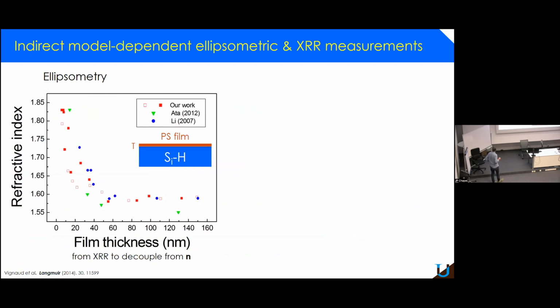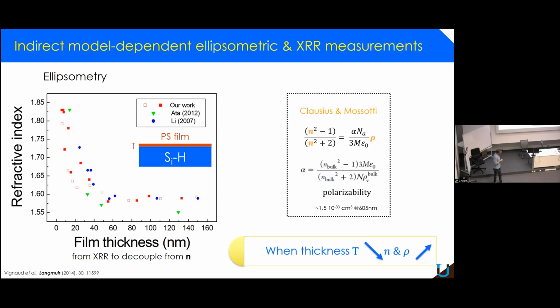So the first one was made by my colleague Guillaume from Lorient. What he did, basically, it's easy. He spin-coated polymer films, and he measured the refractive index of those films as a function of the thickness. And what he saw is that the refractive index did increase quite a lot when the film thickness was very small, up to a value of 1.8 compared to the bulk, which is close to 1.6. The thicknesses here were actually measured by X-ray reflectivity to be able to decouple from the refractive index, because when the thickness is very small, it's very difficult to compute both quantities at the same time. And so if you believe in the Clausius-Mossotti relationship, you can go from the refractive index to the density quite easily. So in fact, the refractive index increasing means that density should increase within the film.